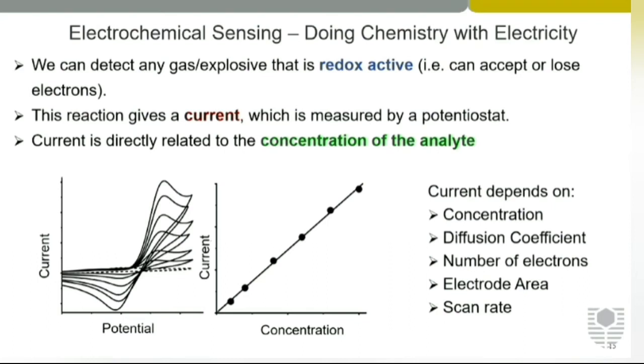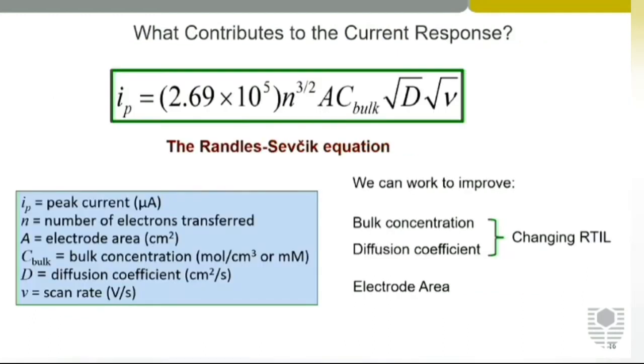The current depends on a number of different factors. I've written them here, but I think it's probably easier to show an equation. I tried to minimize equations, but because this is kind of a phys chem talk, I thought I'd put one in. This is probably one of the most widely used equations in electrochemistry. It shows the relationship between the peak current and some of these other parameters. It says that the peak current is dependent upon some constant times the number of electrons to the power of 3/2, the electrode area, the bulk concentration, the square root of the diffusion coefficient, and the square root of the scan rate.